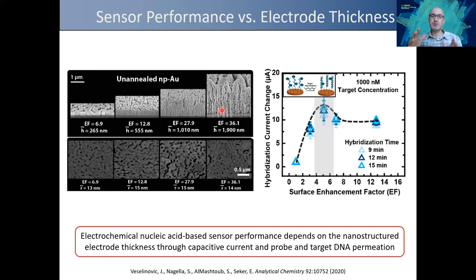And when you have a large porous structure, you have high capacitive currents, which is background noise in essence. And that basically buries your signal, the Faradaic signal, in that capacitive signal. So we created these different thicknesses and used the MB tag probe morphology and did real-time hybridization studies, seeing that as you increase the surface enhancement factor, which is basically a surrogate for the thickness, eventually you reach a point that you max out in your limit of detection, which is the highest current you get here, and eventually it begins to drop and plateaus.